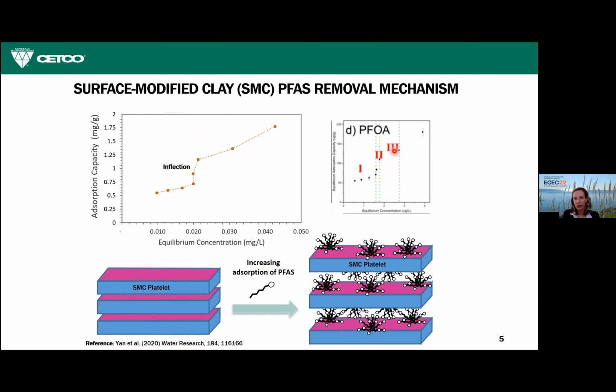And here's the actual data just showing that step change. So we see this with every single PFAS compound that's been tested, which is a good 18 or so different compounds tested in the laboratory. So I guess the conclusion is that this is not a surface area driven mechanism like you would get with granular activated carbon or GAC. It's a unique property in that the reactive area of the surface modified clay actually increases as you increase the PFAS concentration.